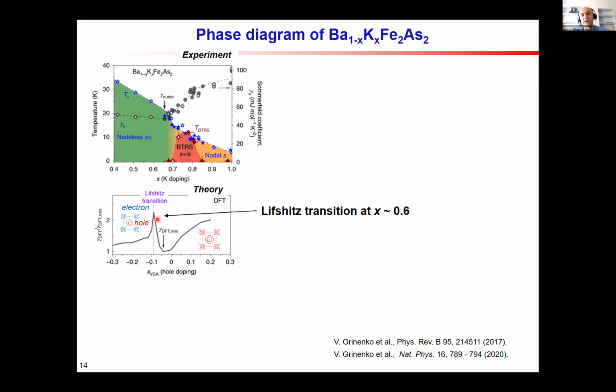So there are several reasons why this sharp peak may not be observed in the experimental data. One of the reasons is that the experimental Fermi surface is more three-dimensional than the theoretical one. The second reason is that the measurements of the Sommerfeld coefficient were performed at rather high temperatures, above 20 Kelvin. And of course, this will smear out considerably the sharp anomaly. And the third one, of course, is defects. Defects also will result in smearing.